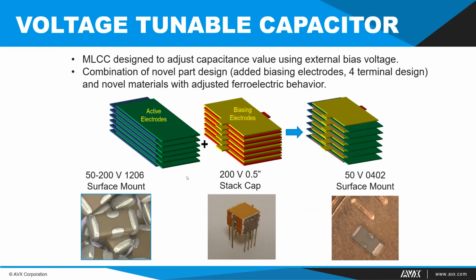And we made this in a couple of different formats. On the right side, you can see what's called the 1206, about 1/8 of an inch by 1/16 of an inch long device. We constructed some prototypes of stacked capacitors that could use this kind of characteristic for higher voltage applications. And we also made a very small 0402 device using plated termination technology that allows us to make a small form footprint device out of this material too.